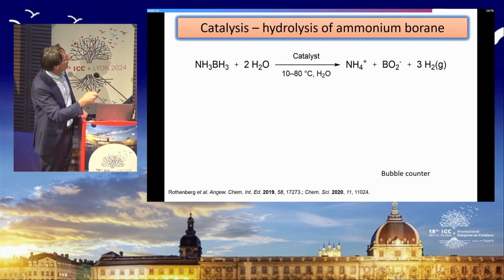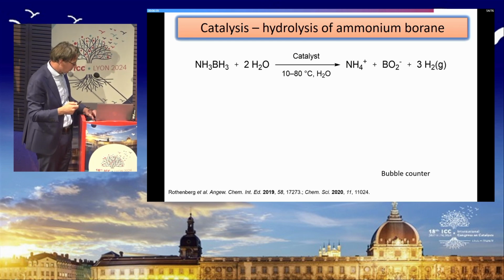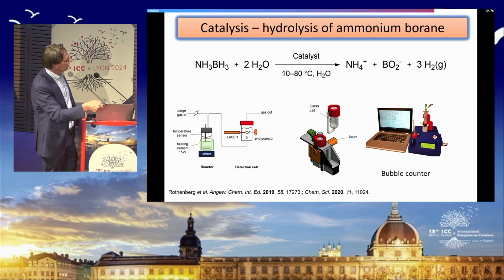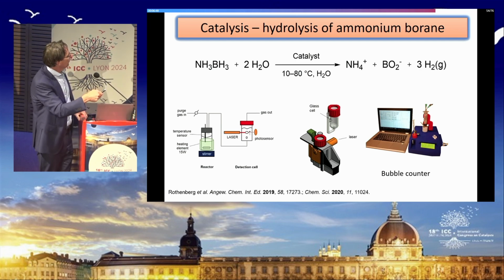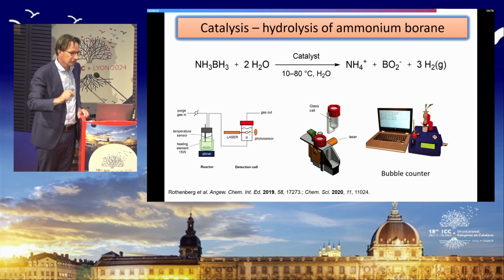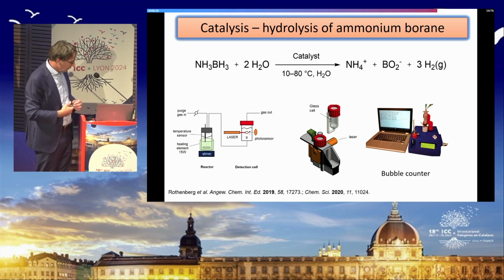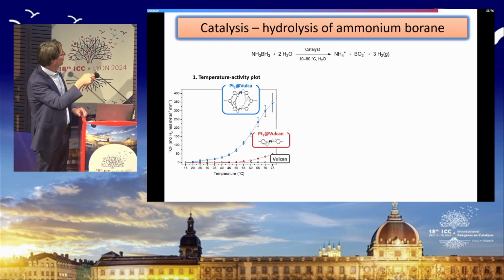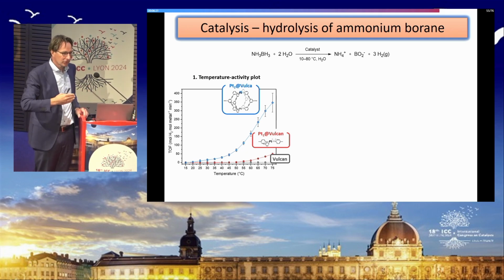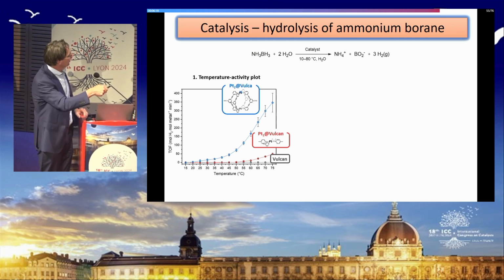Next, we looked into hydrolysis of ammonium borane as the model reaction for this. So you can use a catalyst for this hydrolysis, and hydrogen evolves, and in the group of Gadi Rothenberg, they developed the so-called bubble counter, and you see a sort of display of that here. And it's a very interesting machine because it counts the bubbles very accurately. And then you can calibrate these bubbles, and you can do kinetics, very precise kinetics, with this very simple machine. So as we form hydrogen, we use this bubble counter to follow kinetics. And here you see the results, so we can determine the turnover frequency as function of the temperature. So we ramp up the temperature in time. And because it's so accurate, we can have turnover frequencies as function of temperature.